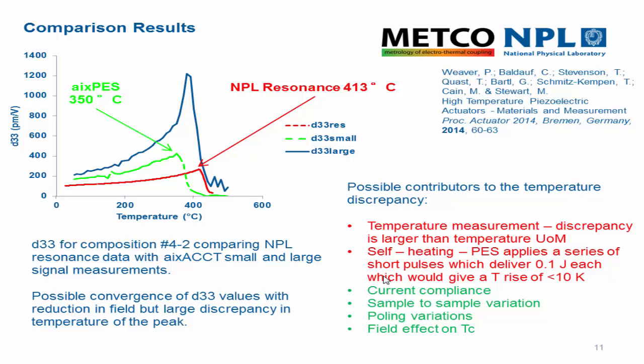It's also been mentioned, the effect of current compliance. So when we get to the peak in this curve here, then we're starting to see the limit of the current capability of the amplifier. So it starts to drop off the voltage. And so on the high field measurements, that could certainly be a factor.